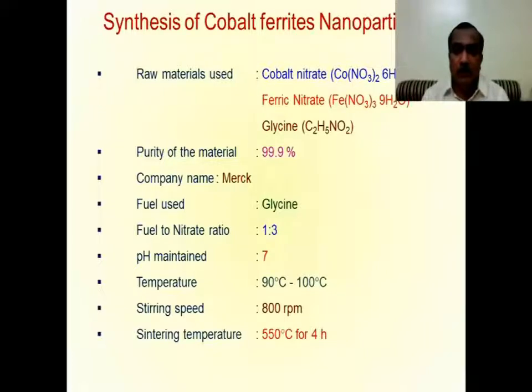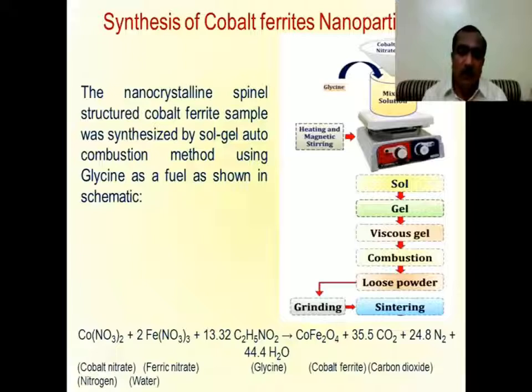The fuel used here is glycine. As I mentioned, fuel is important for the combustion process. The fuel to nitrate ratio is also one of the important parameters in deciding the synthesis procedure. The fuel to nitrate ratio was chosen as 1:3. Then pH is also to be maintained. It is maintained at 7, that is neutral. The temperature varies from 60, 90 and 100 degrees centigrade. For all the synthesis of this cobalt ferrite, we need the magnetic stirrer, and the stirring speed is maintained at 800 rpm. And once the nanoparticles are prepared, they are sintered at 500 centigrade after thermal studies for 4 hours.